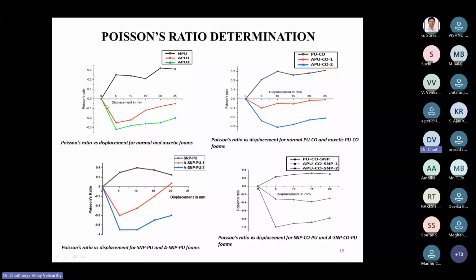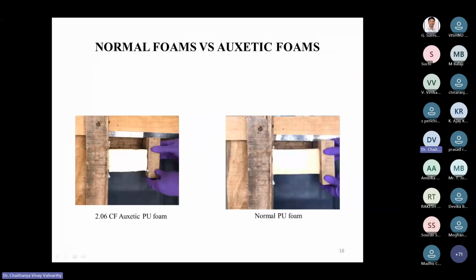If you see here, some foams are having negative Poisson's ratio. This is a normal foam, these are auxetic foams. So they consist of negative Poisson's ratio values. Only to a certain extent will this auxeticity lie inside the foam. If you stretch this foam for a certain displacement, it behaves as an auxetic material. But if you stretch more than that, like 20 mm, 30 mm, more than 30 mm, it behaves like a normal material. So this auxeticity lies inside the material only for a certain time. That is shown here in this graph.